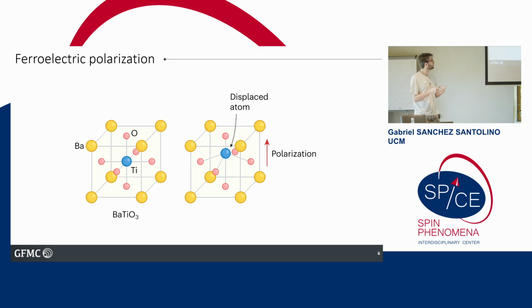If we have a ferroelectric state, then the positive atoms, like the titanium, and the oxygens will be displaced from each other. We will have an electric dipole for each unit cell, and then we have a ferroelectric polarization. Usually, when we have this kind of structural distortion, it is followed by a change in the lattice parameter of the material. It is elongated along the ferroelectric direction, the polarization direction, and constrained in the other directions. And this is the reason why the structures that I'm going to show you were not supposed to be stable.